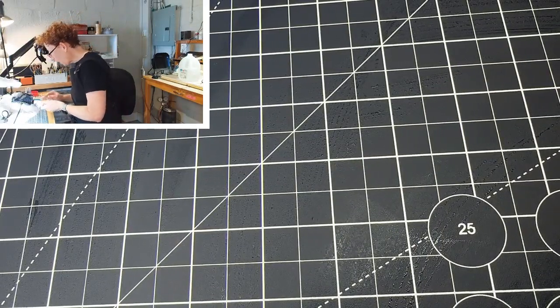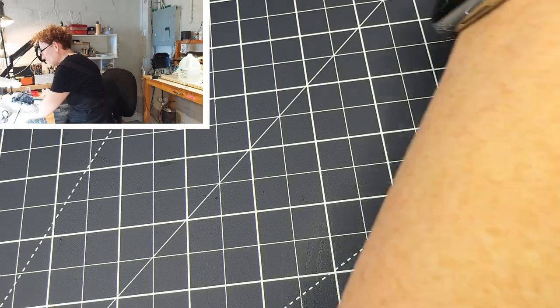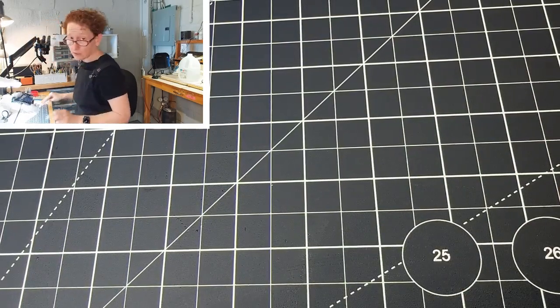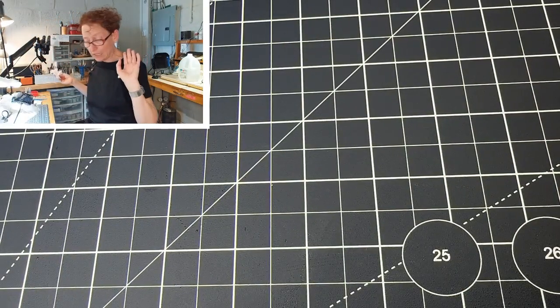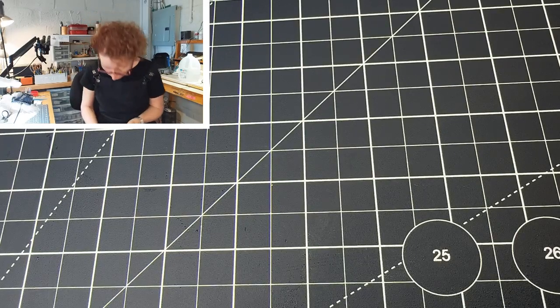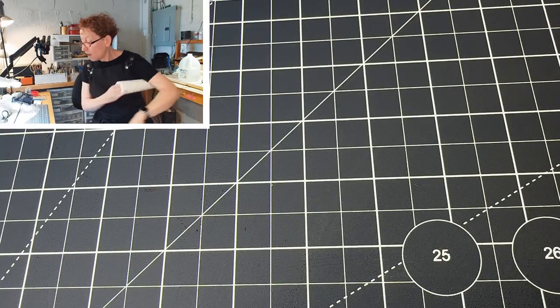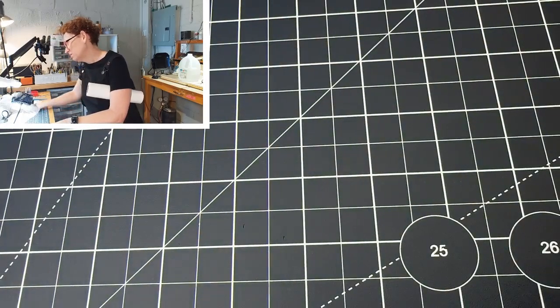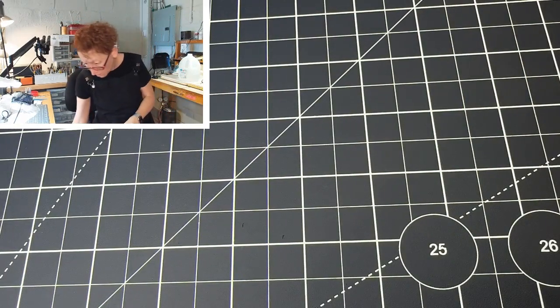And we're going to do all the wires first because it doesn't really matter at this point how many times this bracelet goes in the kiln. I used to think it would matter a lot. It really doesn't. That huge bracelet went in the kiln 30 times and it was fine. Once you hit those oranges, the clock starts ticking as to how many times you can put it in after that before those oranges go brown. But right now we just have some black enamel, some clear enamel. We're quite literally just going to do the wires.